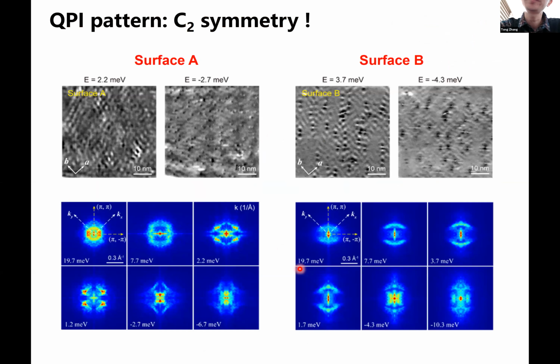So we perform the QPI measurement and do the dI/dV mapping on the surface. Now you can see on surface A, the most commonly observed surface, it shows a C2 symmetry. That's the symmetry breaking. The FFT pattern of the real-space mapping is twofold symmetric. On surface B, the anisotropy is even stronger, and now you can see the FFT gives two arc-like features.